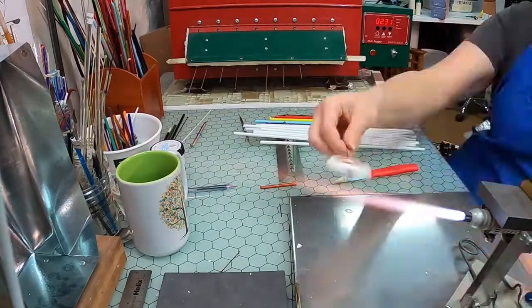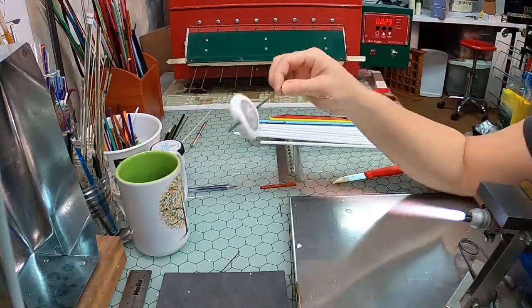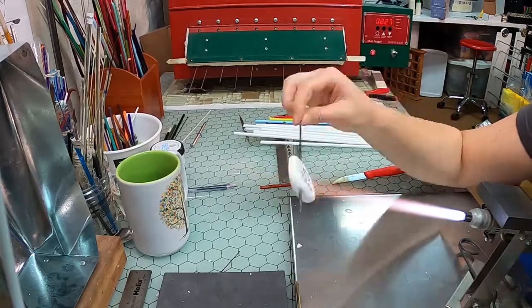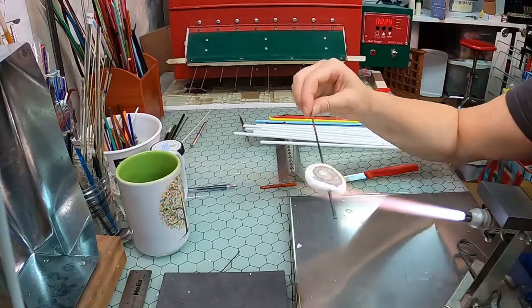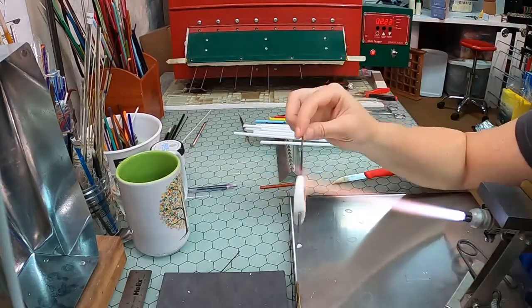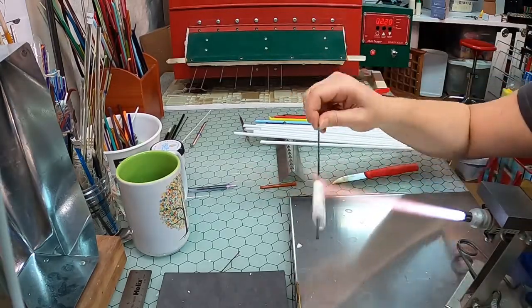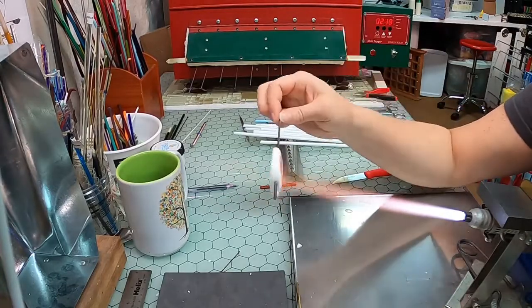I use my minor bench burner for a smaller, softer flame, and I work well away from the candles to keep from boiling my paint, which can happen very quickly if you get too hot for too long, burning away your colors and bubbling your black lines. The colors, so matte and dry when unfired, really pop once all that binder has been burned away and the glass powder has only the white bead backing to contend with. Each bead gets the heat setting treatment and then goes back to suspension in the kiln for another annealing cycle.